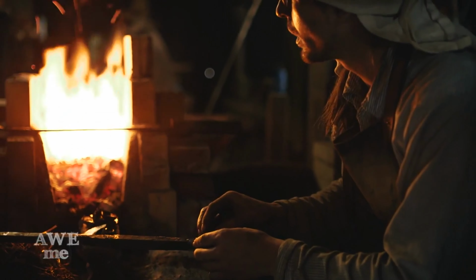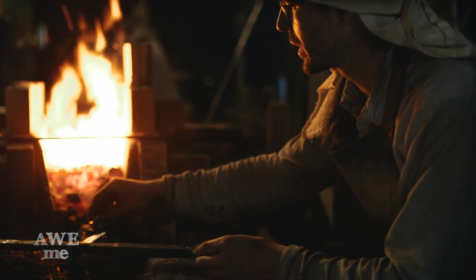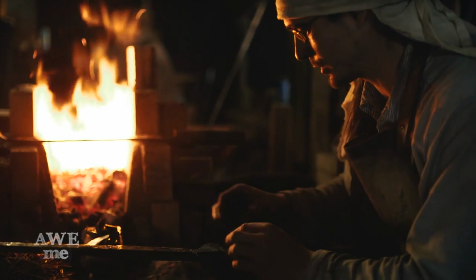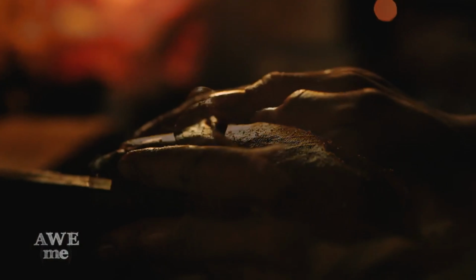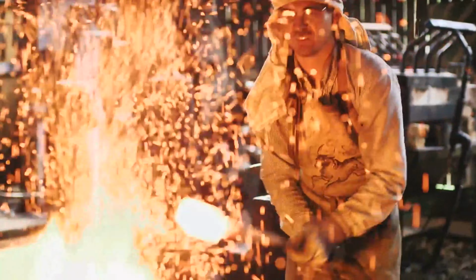Every time the steel is folded, it loses carbon. Said element is spread evenly across the billet and the slag inclusions are squeezed out of the material. When the steel billet is heated, it reacts with oxygen in the air and forms dark scales that are visible on the surface. It is extremely important that said scale won't end up in between the folded blocks. Those scales are rust, and having them in between the layers of the steel would be harmful for the blade